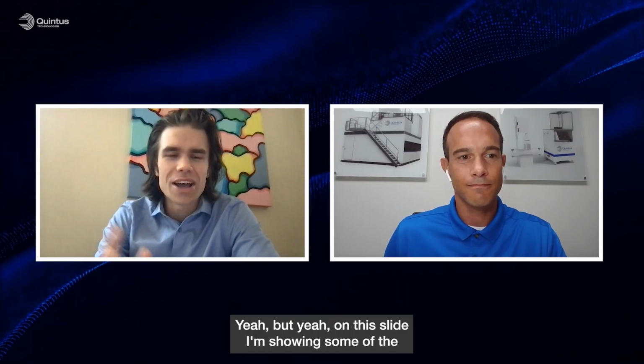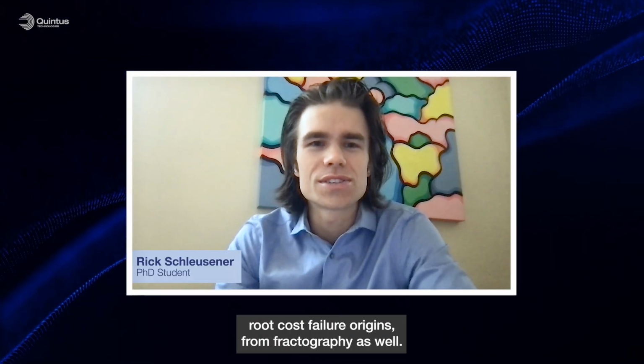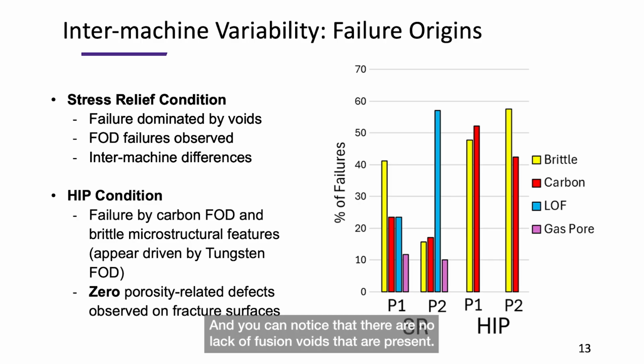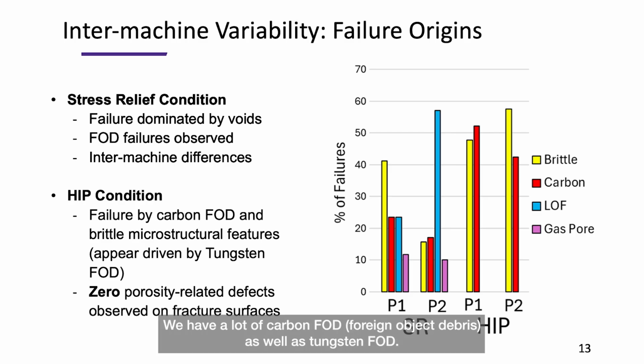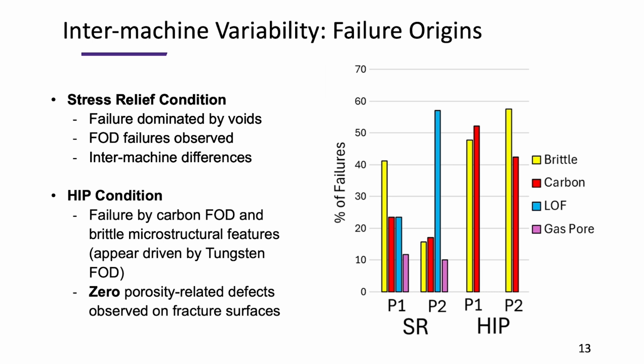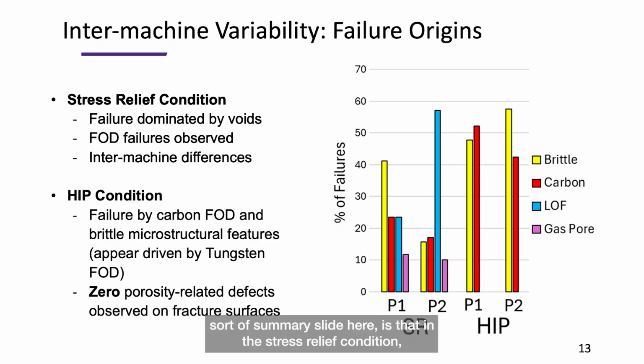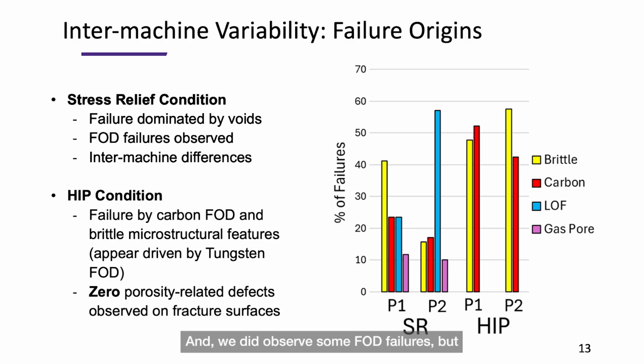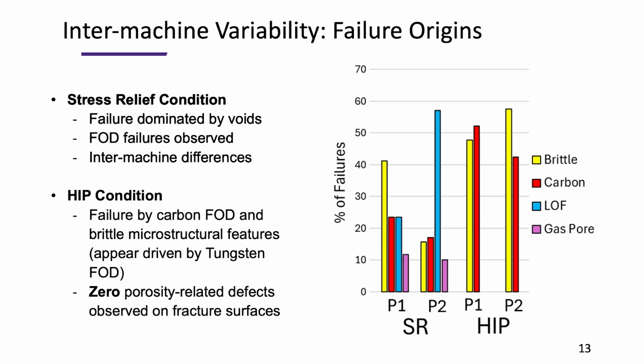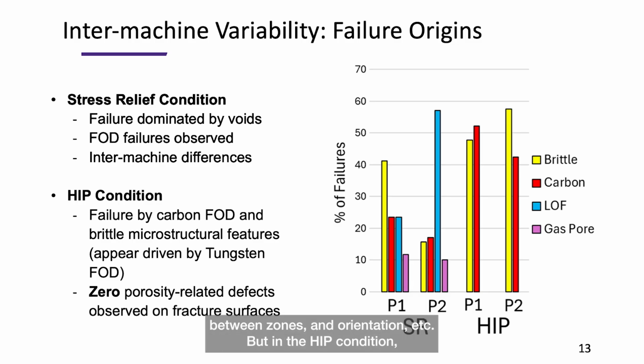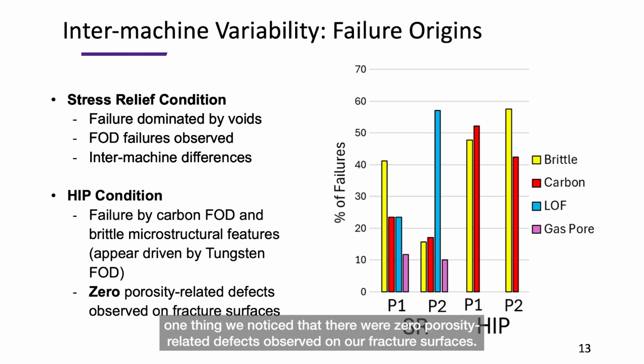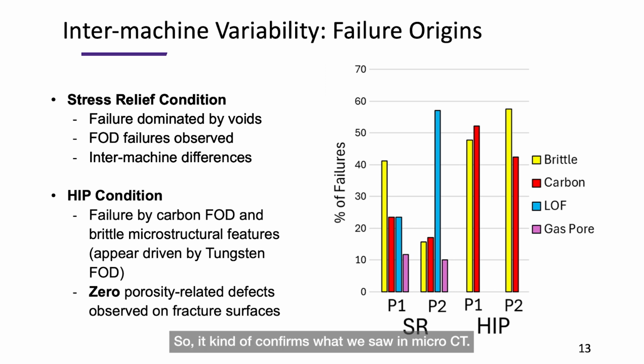Yeah. But on this slide, I'm showing some of the root cause failure origins from fractography as well. And you can notice that there are no lack of fusion voids that are present. We have a lot of carbon FOD as well as some tungsten FOD failure origins that I'm showing here. So leading to our next summary slide here, in the stress relief condition, we saw that failure was dominated largely by porous anomalies. And we did observe some FOD failures, but there were some extensive differences between zones and orientation, et cetera. But in the HIP condition, one thing we noticed is that there were 0 porosity-related defects observed on our fracture surfaces. So that kind of confirms what we saw in micro CT.